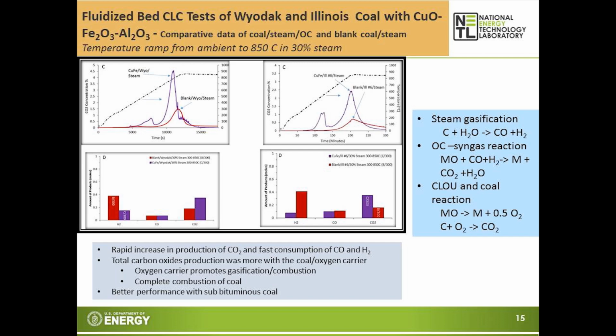These are some of the fluid bed CLC data with Wyodak coal and Illinois coal using the copper iron oxygen carrier. Coal chemical looping combustion involves several reactions. The coal reacts with steam to produce carbon monoxide and hydrogen, and then the syngas, the CO and hydrogen, reacts with the metal oxide oxygen carrier to produce carbon dioxide and water. In addition, when you heat up the metal oxide, it can also produce oxygen, and that oxygen can react with coal to produce carbon dioxide.